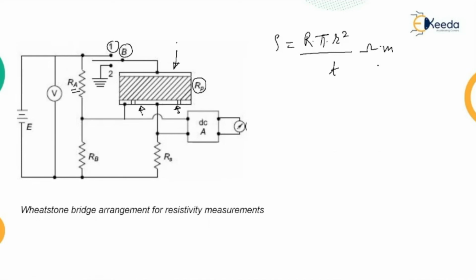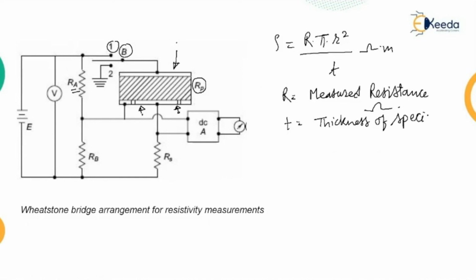R into pi r squared divided by t ohm meter. R is the measured resistance in ohms. t is the thickness of the specimen in meters, and small r is the effective radius in meters. So using this network, the volume resistivity rho for liquid specimen with cylindrical electrodes can be measured, right?